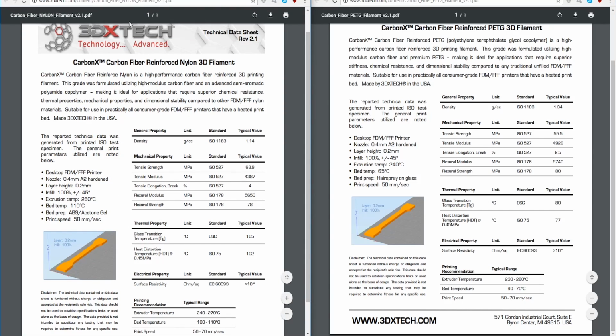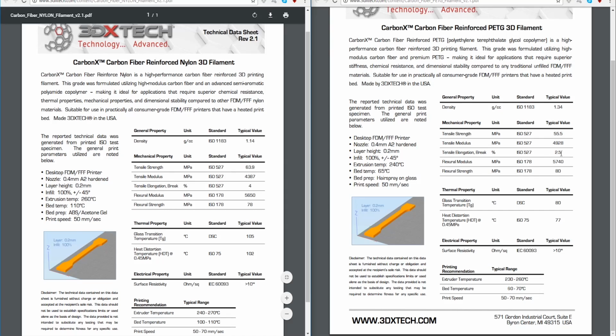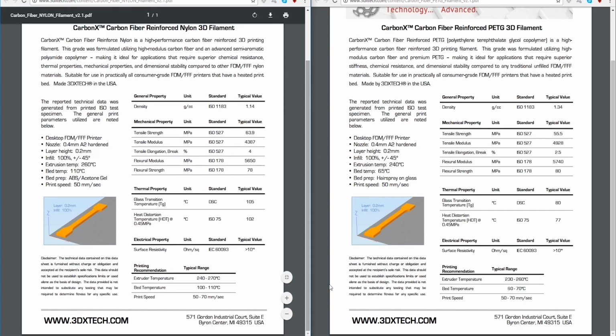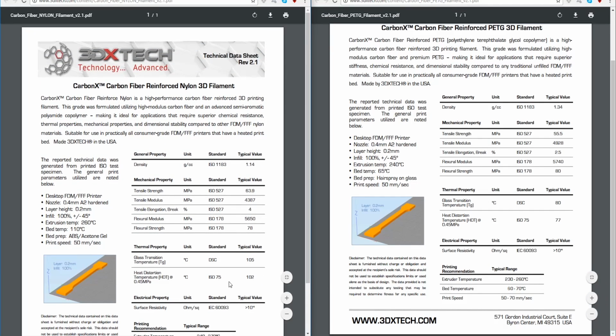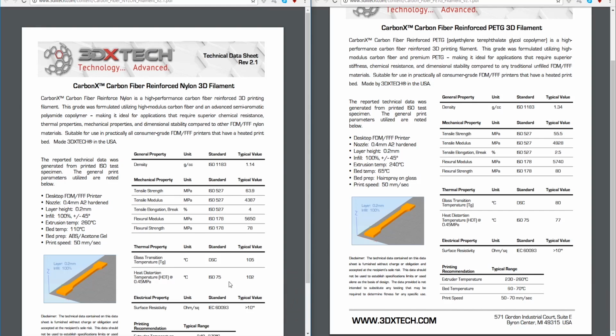Alright, carbon fiber nylon: drastically better tensile strength, almost as good tensile modulus, almost twice as much elongation, almost the same flexural modulus, almost the same amount of strength, higher temperature. So, nylon, and also quite a bit less dense, 0.20 grams per cubic centimeter less.